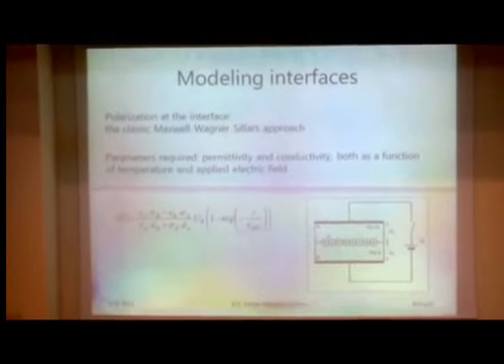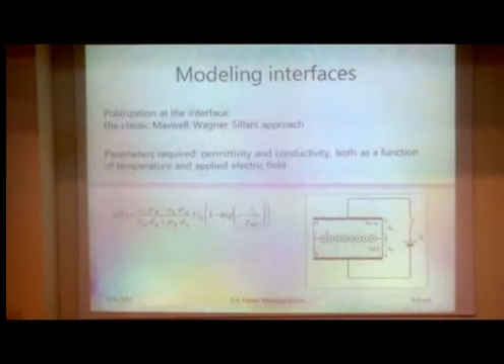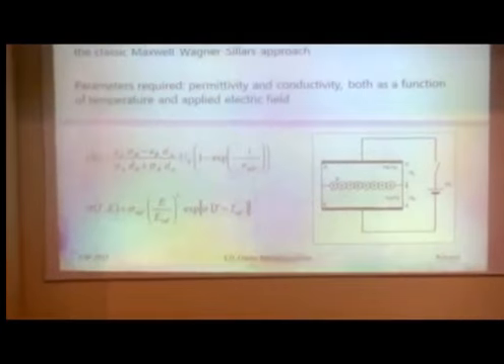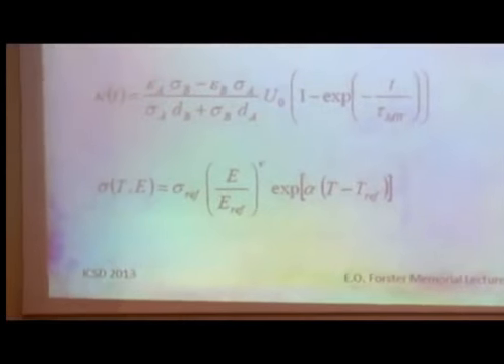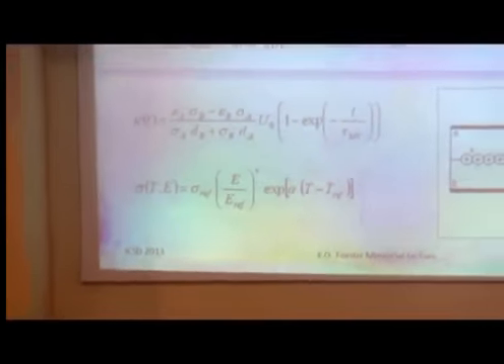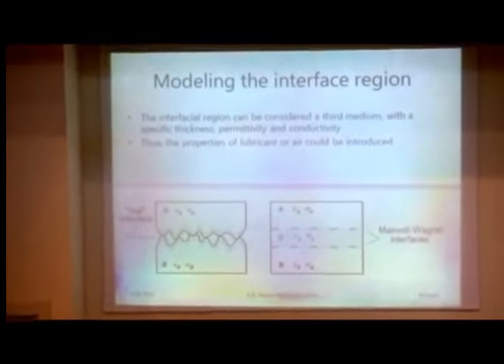Now we know that conductivity is not a constant parameter. It is very strongly affected by temperature and by electric field, in fact. So we have to use an equation for the conductivity which accounts for temperature and for the electric field. So you do that. What are the results? Now I go too fast, sorry.